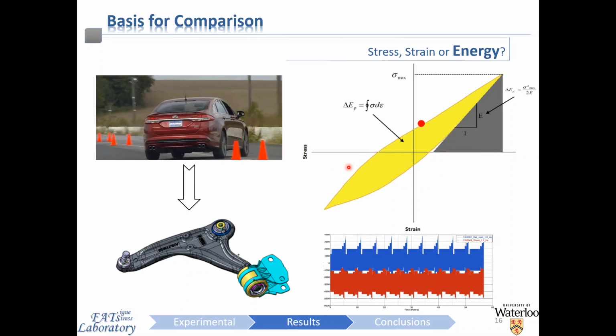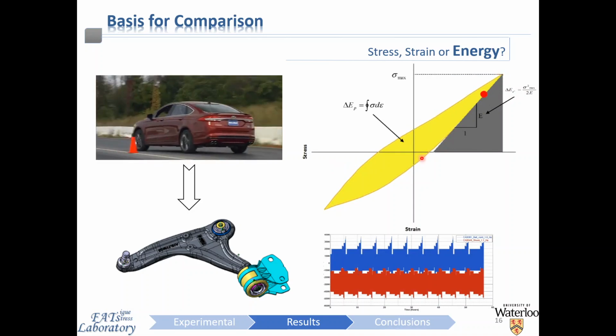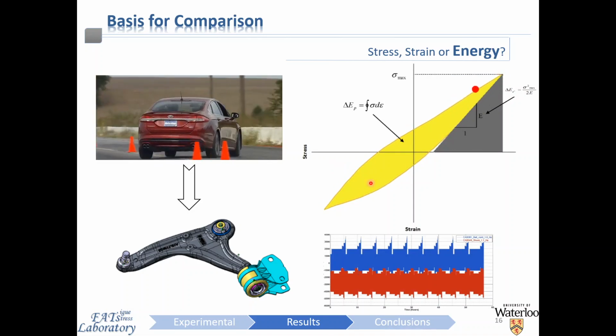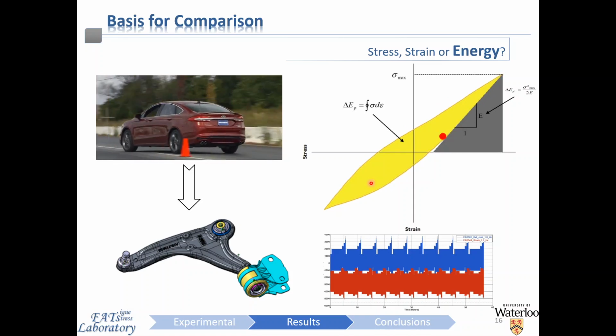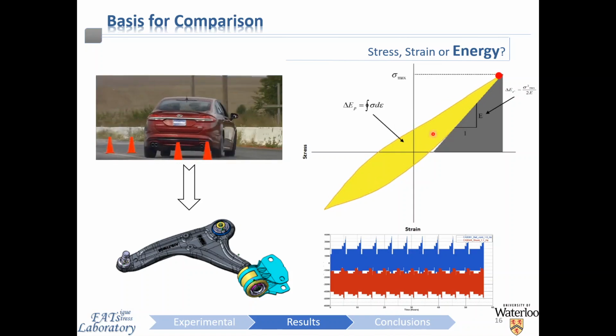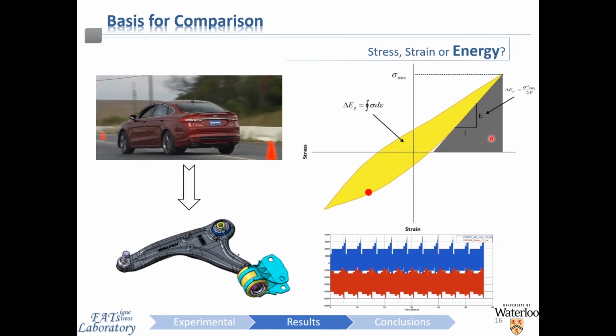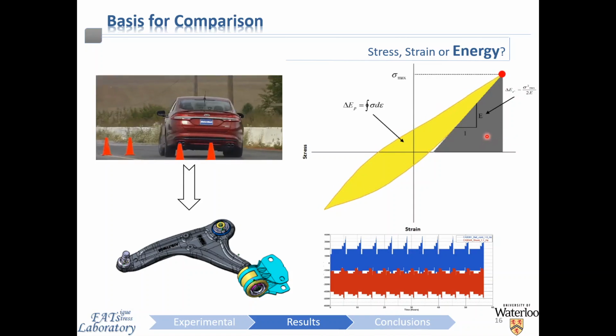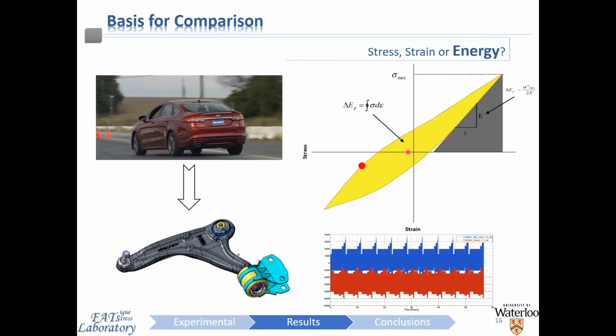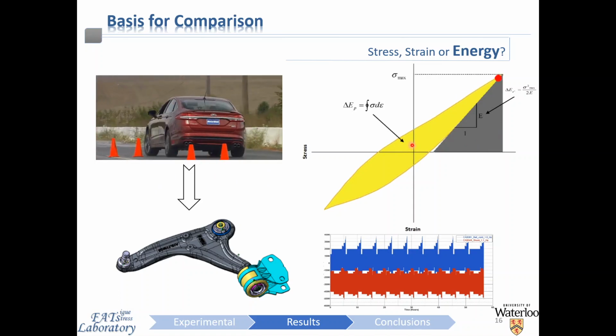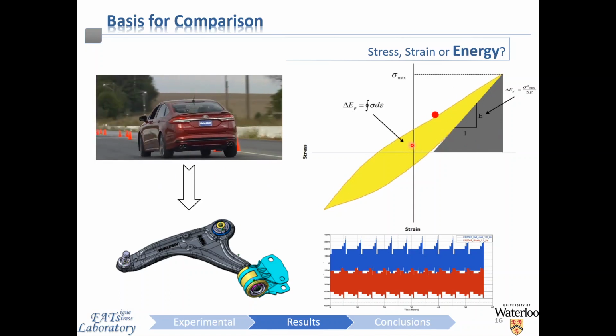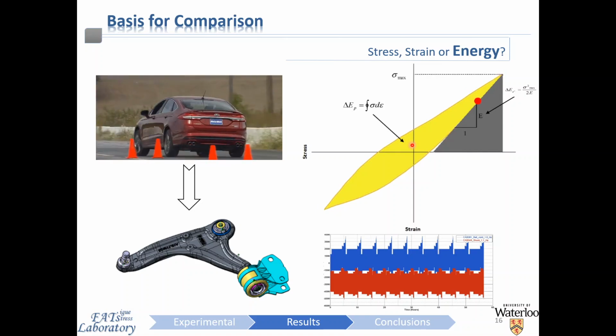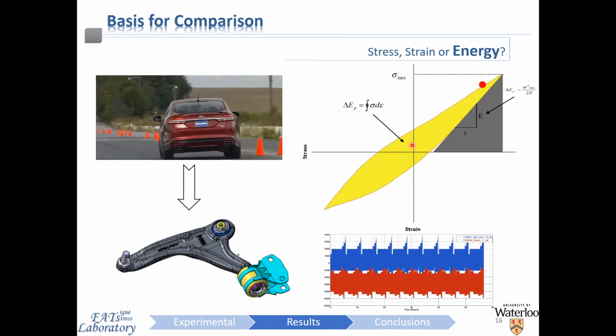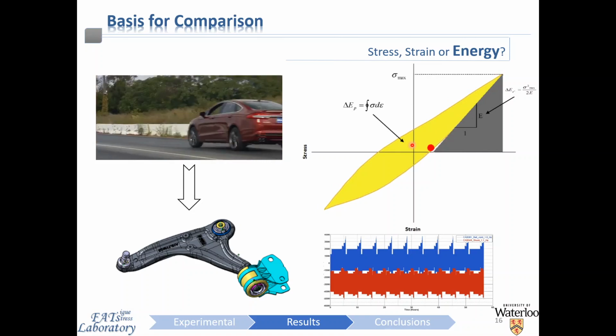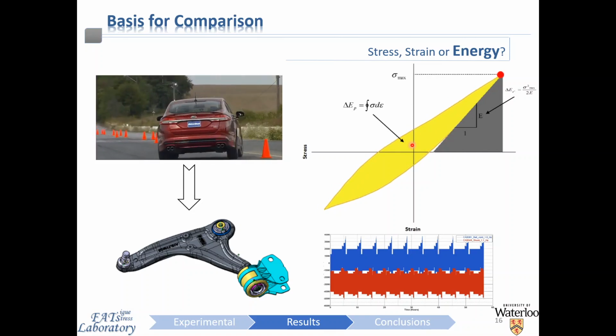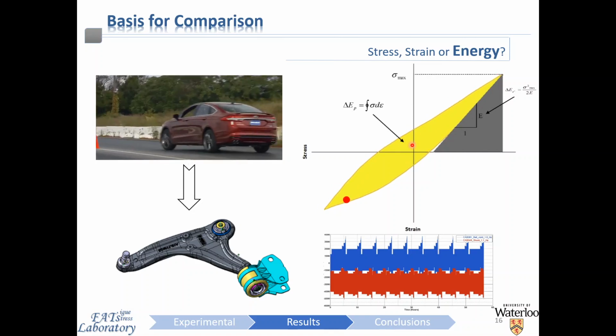Finally, we can also use an energy quantity, the strain energy density, as a basis for comparison. And by energy, effectively what I mean is the combination of the elastic or the reversible strain energy density signified by this gray triangular area on the right, and the plastic or irreversible strain energy density signified by the yellow area enveloped within the hysteresis loop on the left. So now the argument can be made which technique is most representative of the actual loading in the service environment of the vehicle. And the answer is, well, it depends.